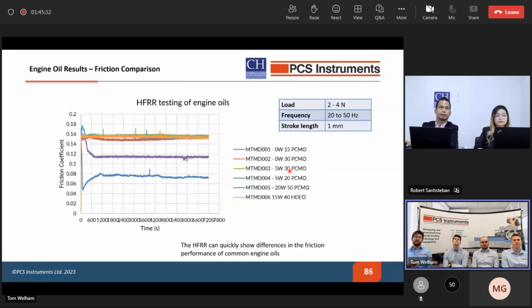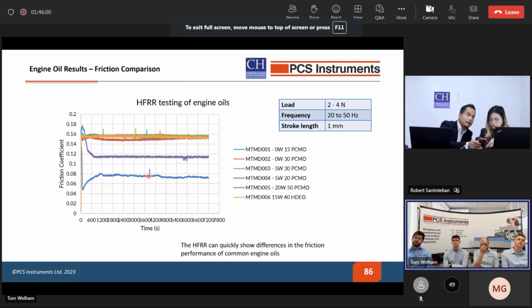Great, there we go. So here's a graph showing several tests of lubricants and the friction traces that were produced. The friction coefficient is recorded throughout the test, and we can see that it does change significantly due to wear of components. So if you get a lot of wear in your test, you can see that friction can go up, like in this specimen oil here. But other oils where you don't get as much wear, it could be quite stable.